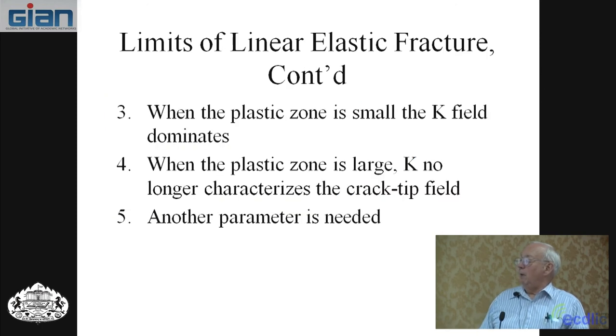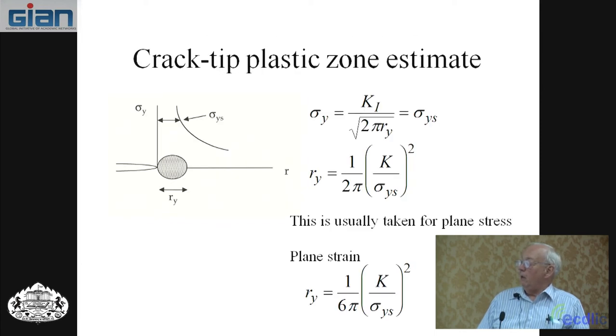If the plastic zone is small enough, it's contained by the K field, and the K field dominates. But when the plastic zone gets too big, the K no longer can dominate, and so it's not a good parameter anymore. So you can only use the K approach when the plasticity is sort of under control. When it's under control, we call that behavior linear elastic fracture mechanics. So the whole stress analysis of Irwin is a linear elastic stress analysis, and to use it, you need essentially linear elastic behavior.